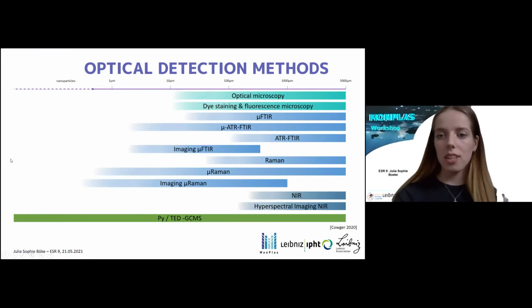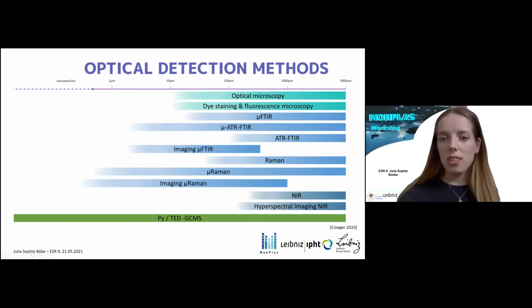Yeah, so as you've seen from all the previous presentations, we talked a lot about different optical detection methods. Therefore, I would like to start with a short summary. Here you can see basically the range, the resolution for which those techniques are more or less applicable. You see that we have already heard a lot of them today, especially FTIR and Raman. And what we see is that especially for the region around 1 micron, 10 microns, it's actually getting quite low when we see what methods we can use for that size range.